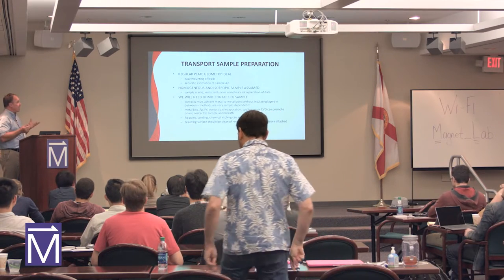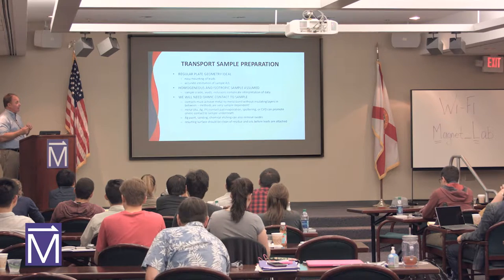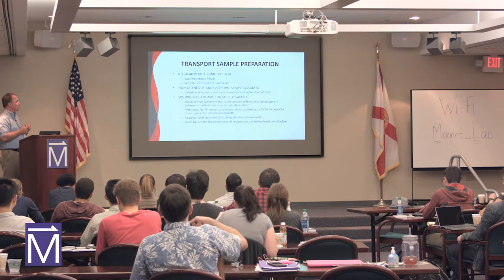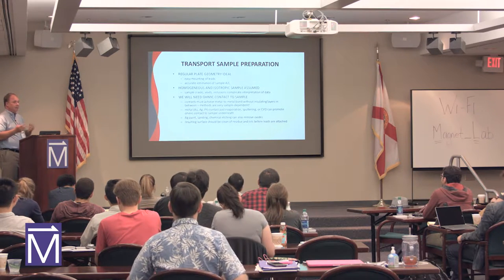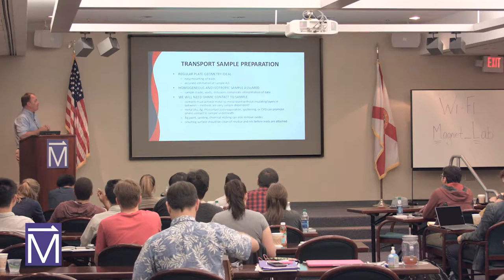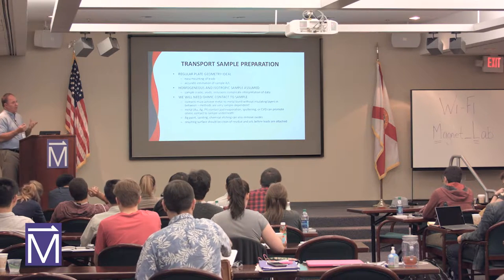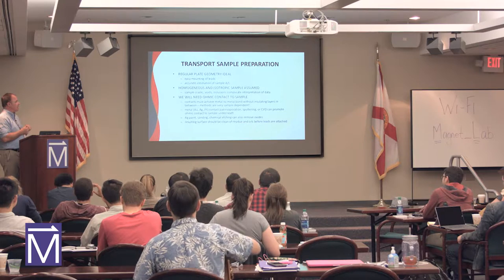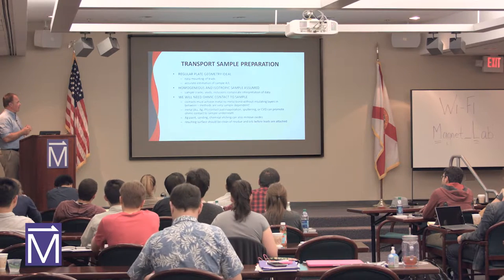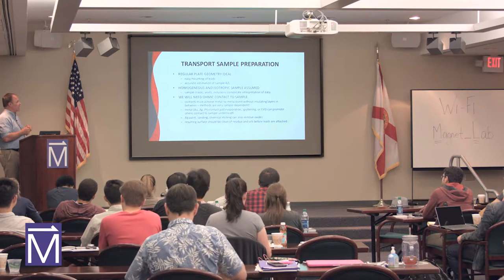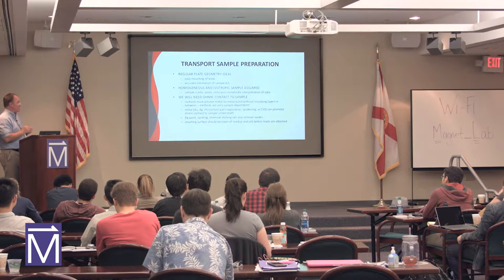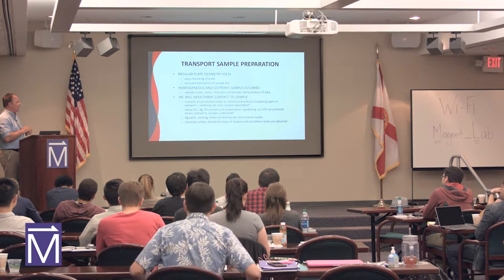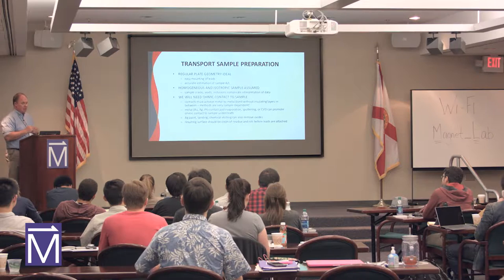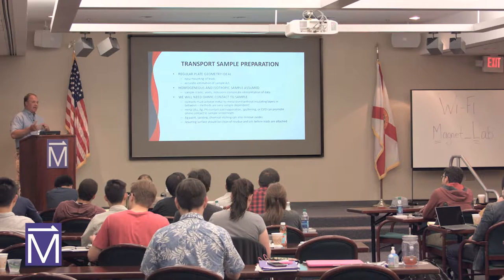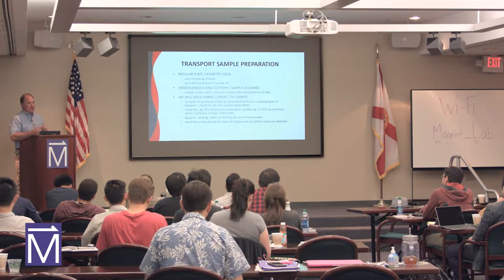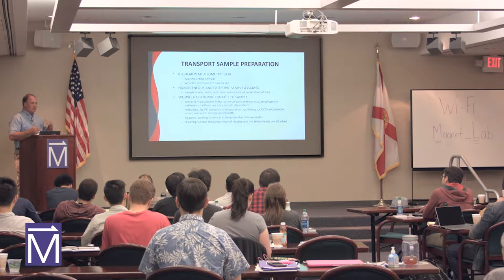How do we prepare the sample? You typically want a plate geometry to put the sample. It's typically what you have. You can measure the dimensions of the sample, the length and the area and the thickness. You want to have a homogeneous sample if you can. Don't have it cracked or any voids in the sample. And you need to make an ohmic contact to the sample. So you want to have good contact between your leads to the sample.